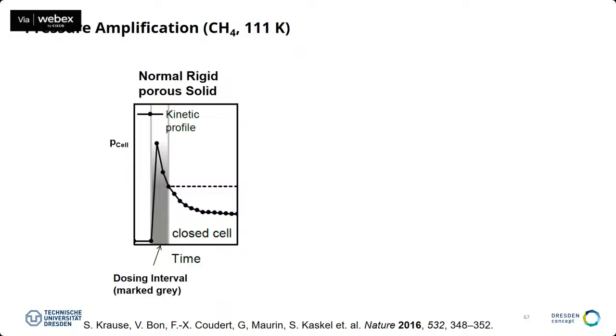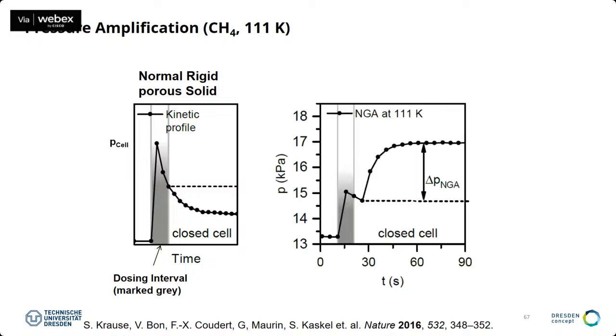So what is so strange here? Normally, when you dose a pressure to your porous material, you will always see that the pressure is decreasing because the porous material is taking up the gas. But in this material, when you dose a pressure to the cell, first the pressure is decreasing, but then it's pushing out gas. It's almost like these mushrooms which are exploding when you step on them. So they push out gas, and this was a quite strange phenomenon.